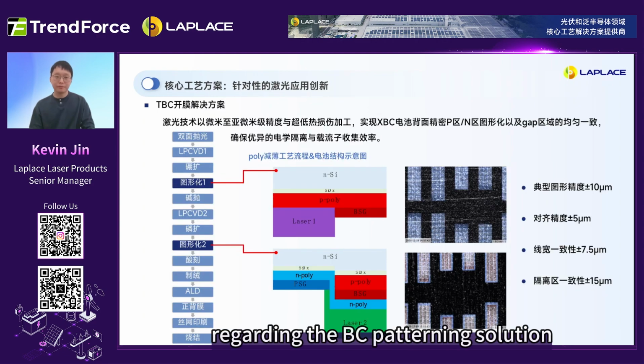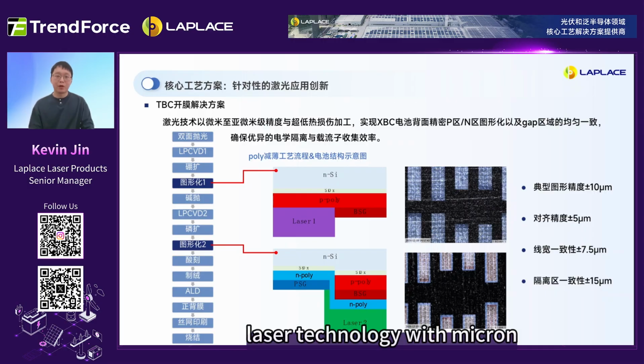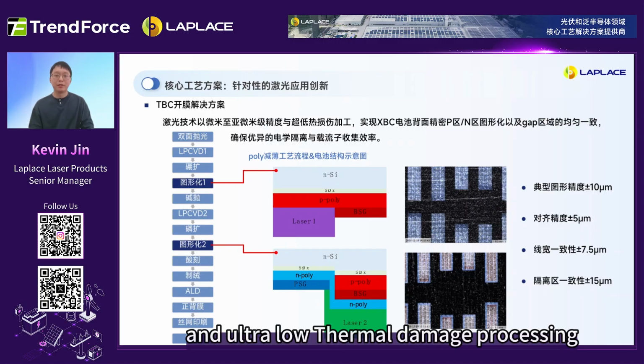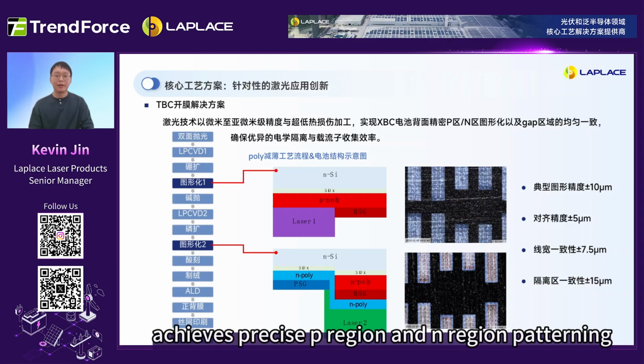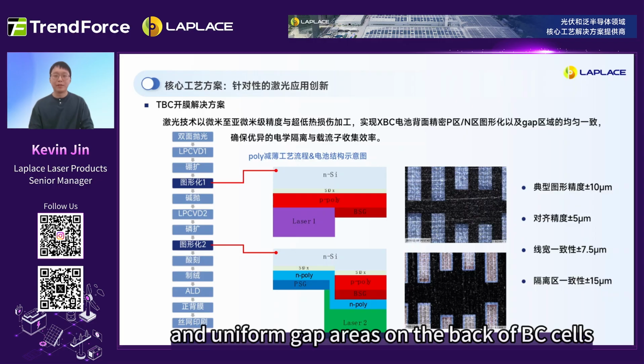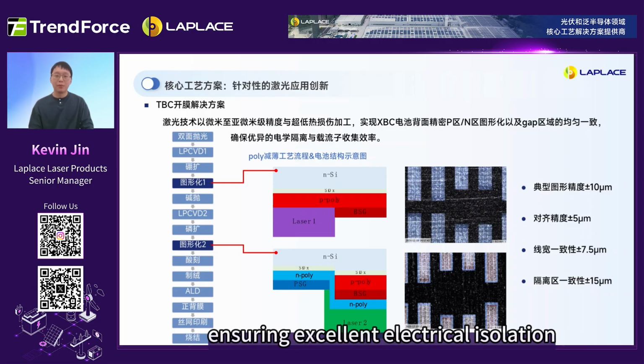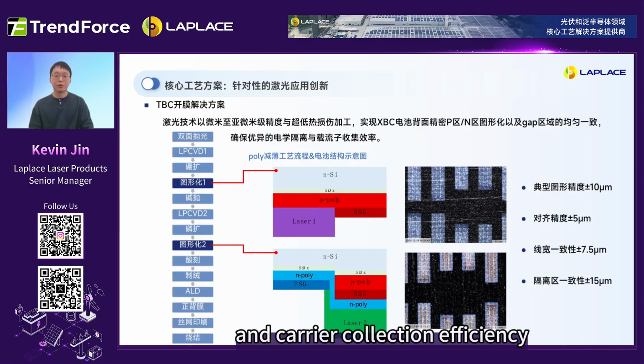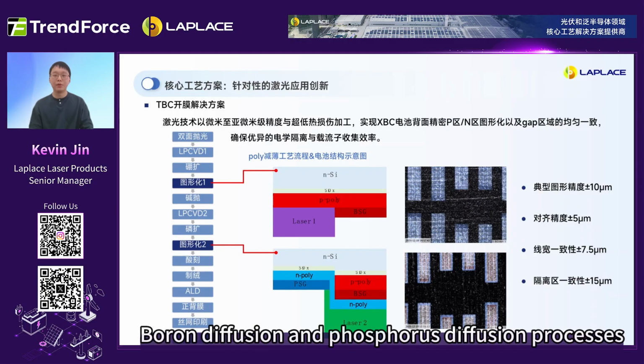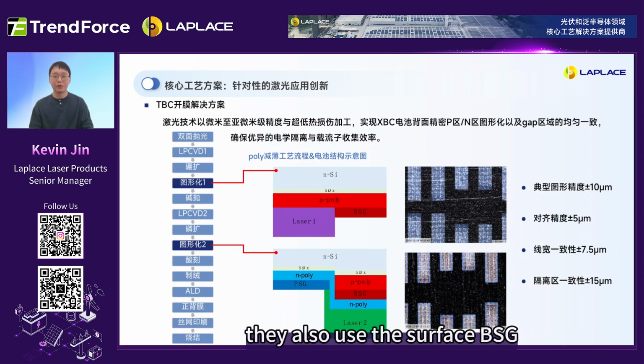Regarding the BC patterning solution, laser technology with micron, submicron precision, and ultra-low thermal damage processing achieves precise P-region and N-region patterning and uniform gap areas on the back of BC cells, ensuring excellent electrical isolation and carrier collection efficiency. From the overall battery process flow, laser patterning 1 and laser patterning 2 are mainly after the battery boron diffusion and phosphorus diffusion processes. They also use the surface BSG, borosilicate glass, and PSG layers as laser absorption layers.